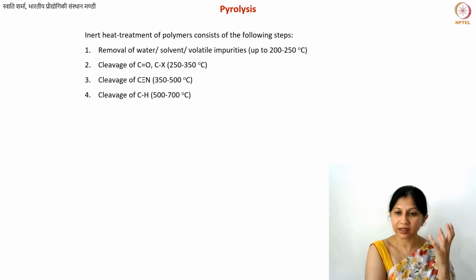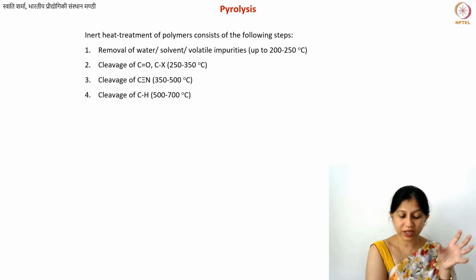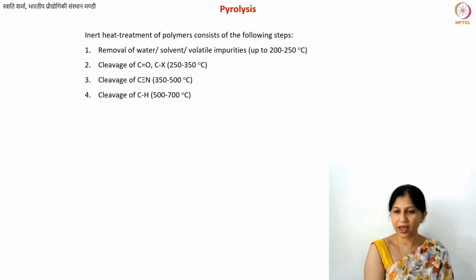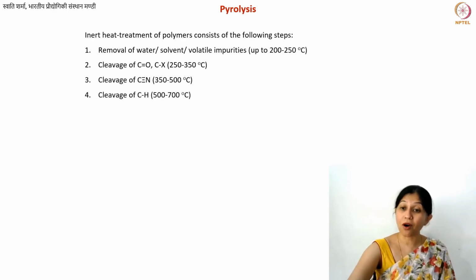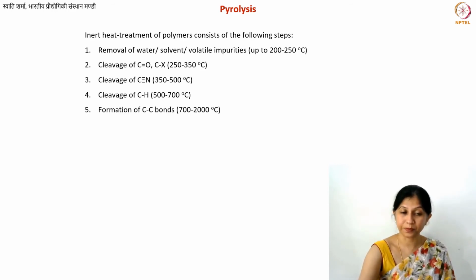So sometimes as soon as they form a smaller hydrocarbon, they are out. And so on. But whatever is left, in most cases around 700 degrees, you will have not a complete decomposition, but an almost complete decomposition of your polymer, and most of the non-carbon atoms are now ready to leave or have already left.